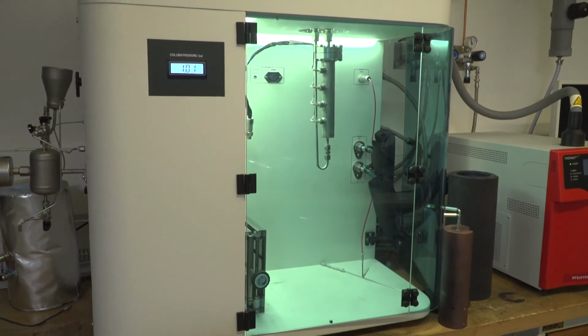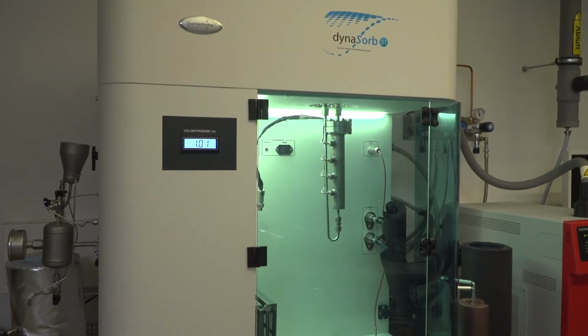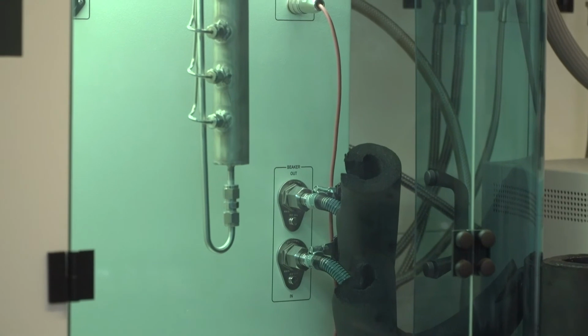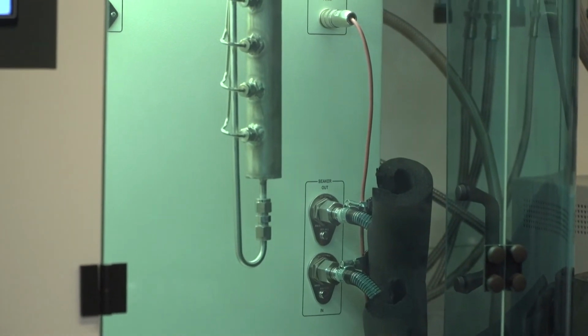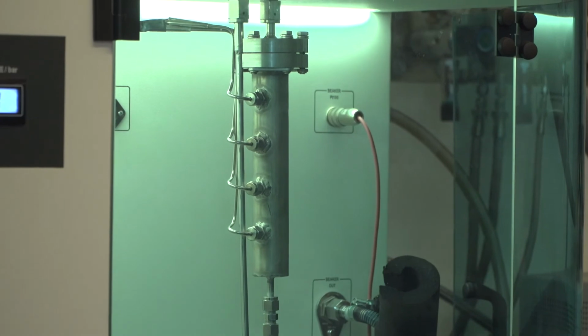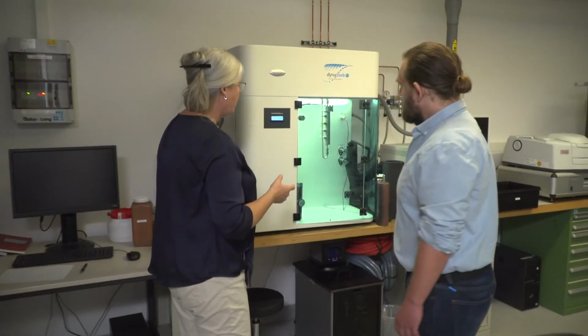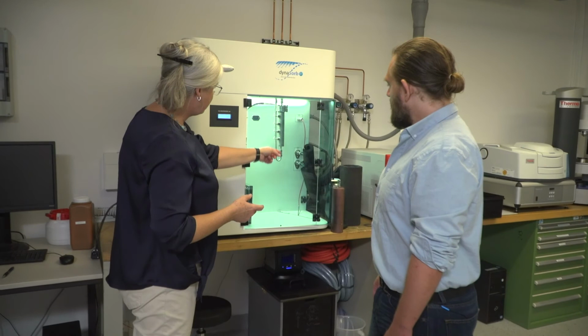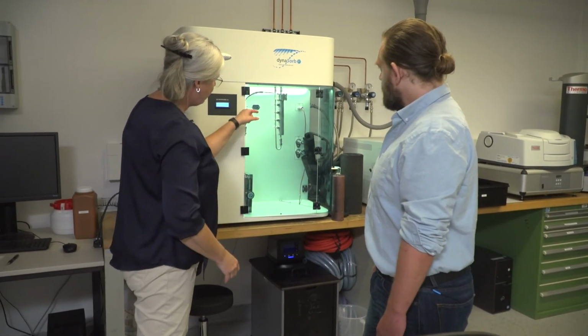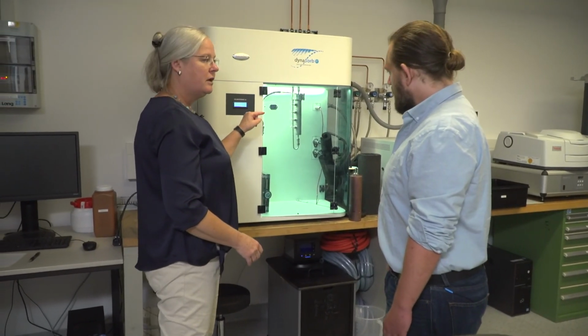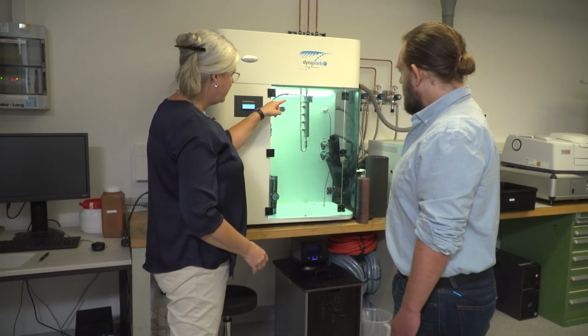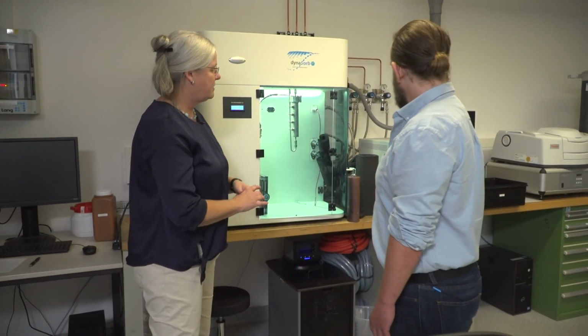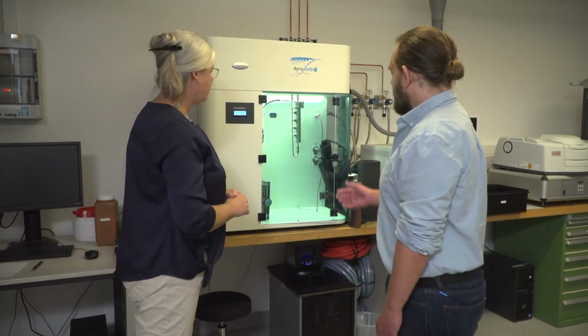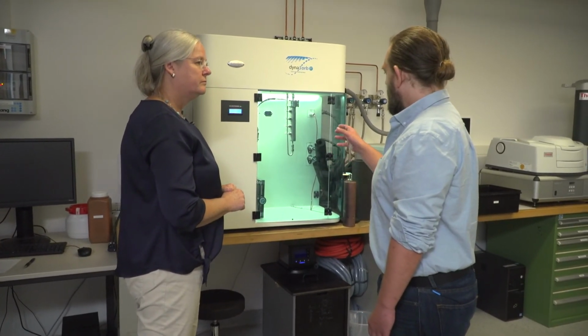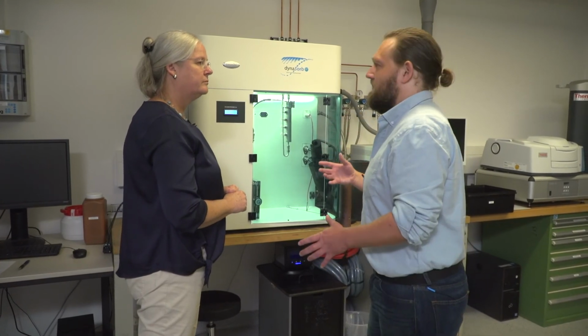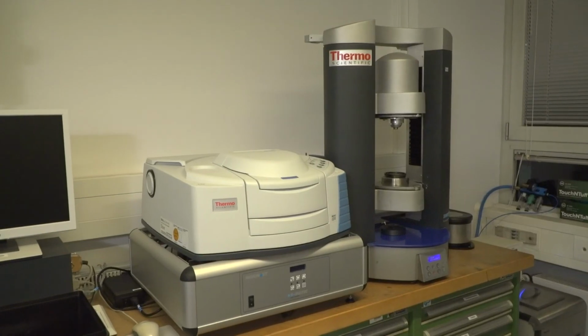What's this thing over here in the corner? This Dynasorb is equipment to measure gas absorption, and we can make a defined composition of gases. We let it flow through the sample, and the sample is inside this tube, and you have 4 measurement places for temperature. Then the absorption takes place, and the breakthrough we analyze with a gas analyzer here. So you can basically tell with the Dynasorb how much of different types of gases your aerogel would absorb.